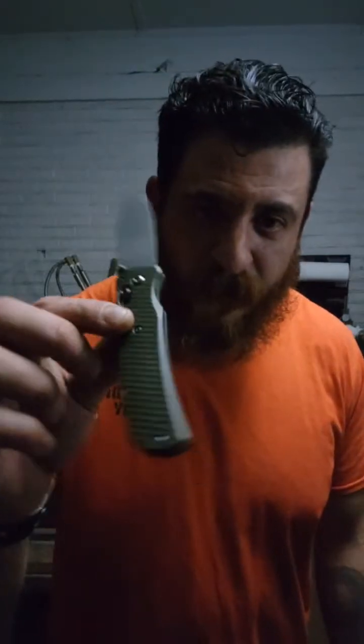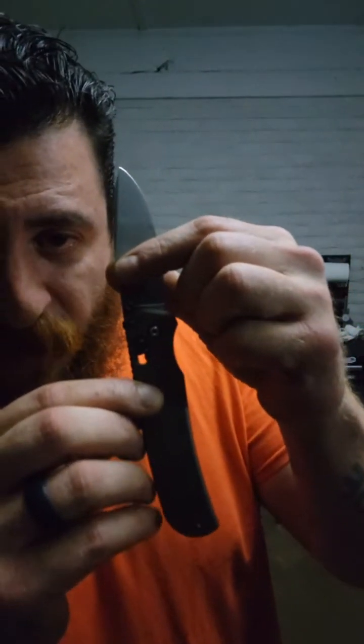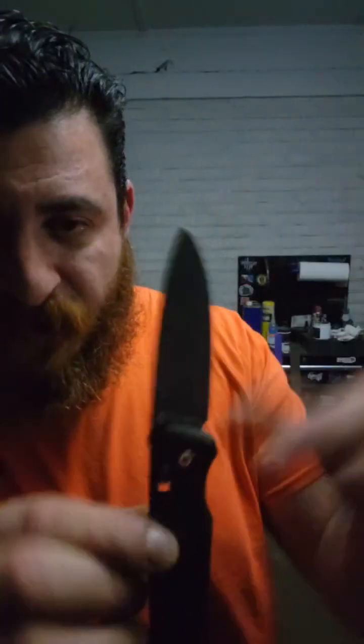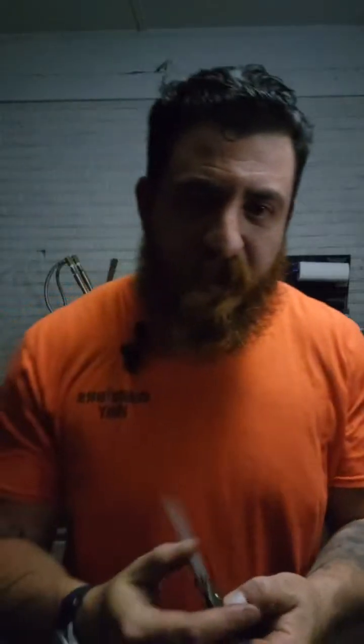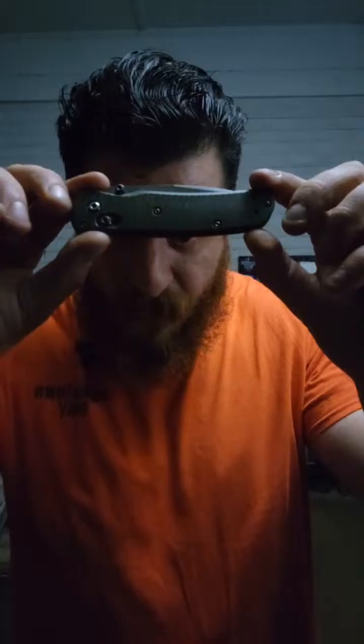Yes, yeah, I reheat treat a lot of my knives. So this was a Bugout. My wife got me this as a Father's Day gift. It was the M390 one with the aluminum scales. And the M390 sucked. So I do this a lot. What I did is I reheat treated the blade, reground it, and then acid stone washed it. So you can see now it's like 64 Rockwell, and it's probably 8 or 9 thou behind the edge. Then I got some cool scales on it because I didn't like those scales very much. Now I've been carrying this for like a year straight almost because I like it that much.